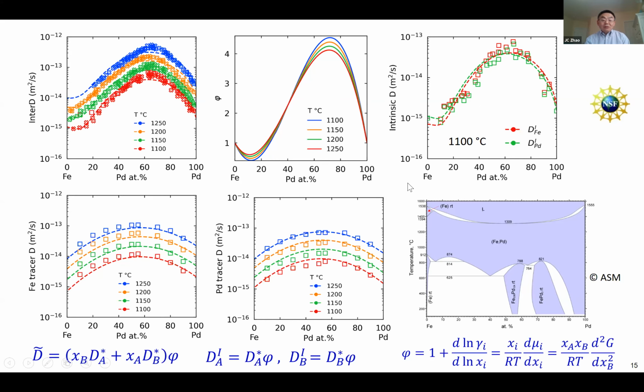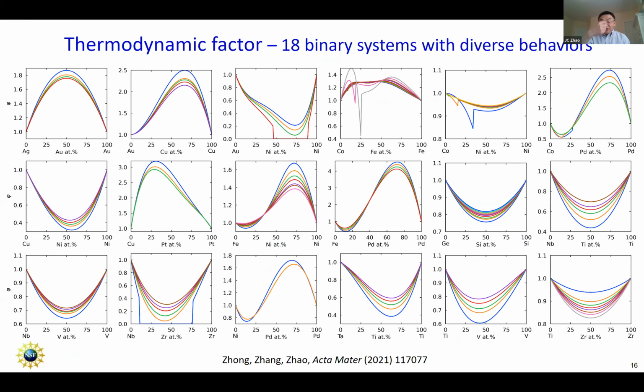Okay. So basically, we found about 18 binary systems for the test. We want to see how many parameters we really need to model the system. You can see we have systems that have very asymmetrical behavior, like those ones, and then we have very symmetrical behavior. We have both positive and negative. So it's a very diverse set of data. We have a lot of good data in those 18 systems, and that allows us to do a very comprehensive test. In some of the systems, the diffusion coefficients differed by 8 or 9 orders of magnitude. Again, a very diverse system.